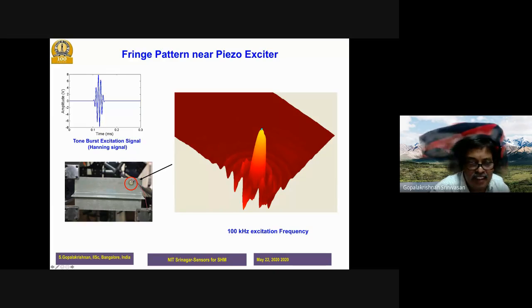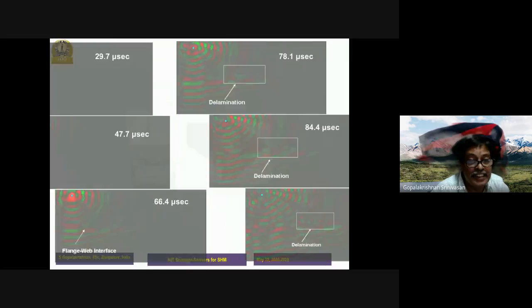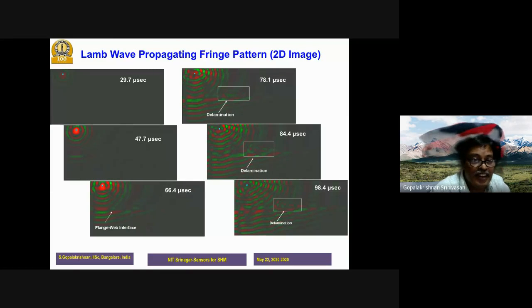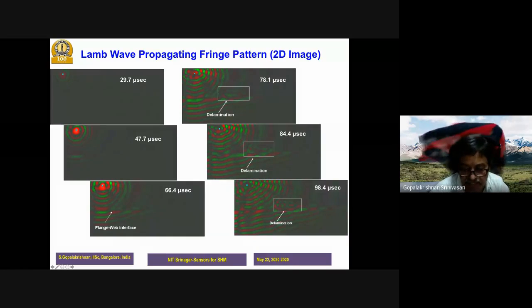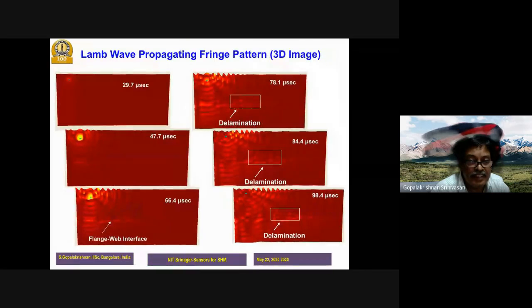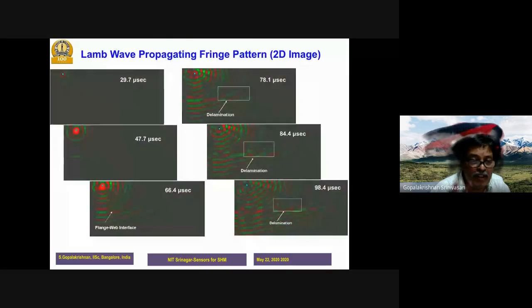So this is basically a 100 kilohertz 5-cycle tone burst signal. If you look at it, this is how it comes. You see, this is the flange-web interface at this time, and it interacts with the delamination at this point. You can easily see there is mode coupling happening. It can be easily visible. This is taken from only one head.